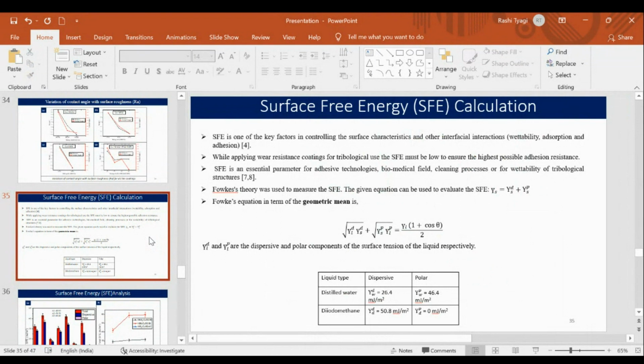So basically wettability means when the droplet makes contact with the solid surface, and it also depends on the surface free energy. Surface free energy means the extra energy that a surface has due to intermolecular attraction. When the water comes in contact with the solid surface, there will always be an intermolecular attraction between the water particles and the surface. So if the surface energy of the solid surface is higher, then it will attract the water, and the surface becomes hydrophilic.